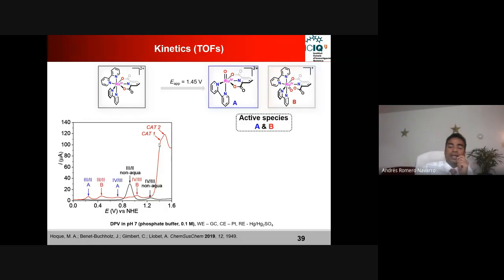And then we figured out that when we are applying the potential at 1.45 here, so basically when we have this ruthenium-4 compound, all of this bipyridine ligand is going out, and then the water is coming, because all this chemistry is happening in water. And then forming this compound, active species A, that I already showed you, that has a lower overpotential, but the turnover frequency was very low. And then another species is this active compound B.